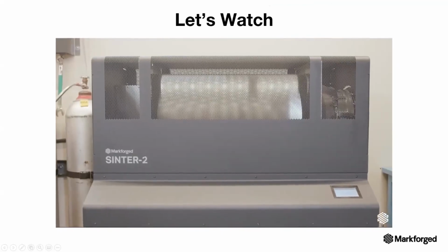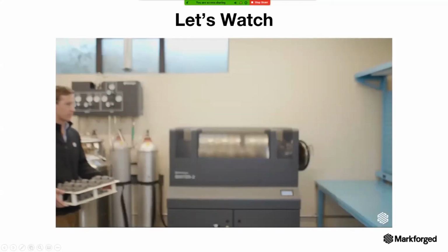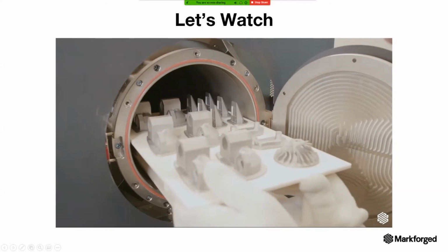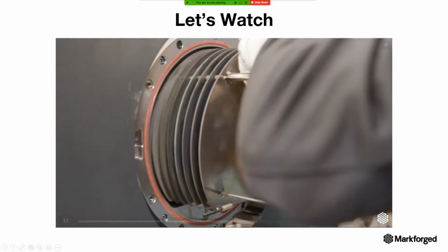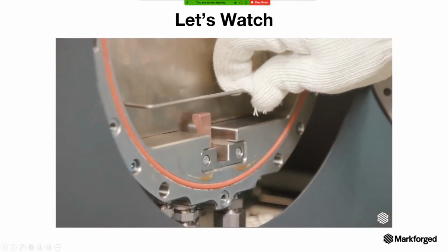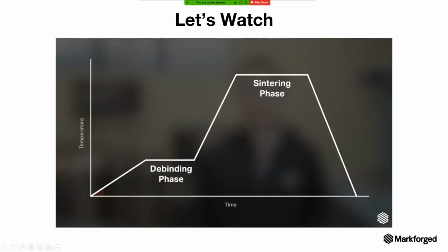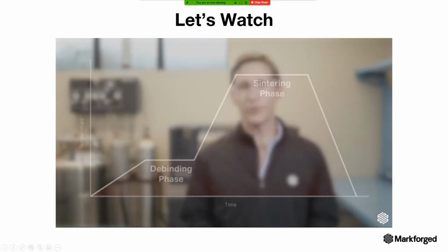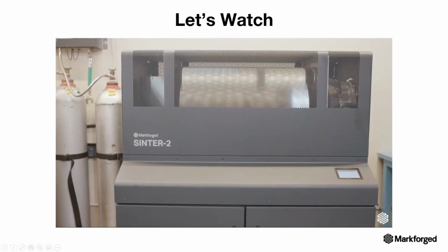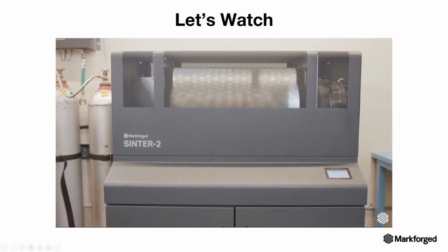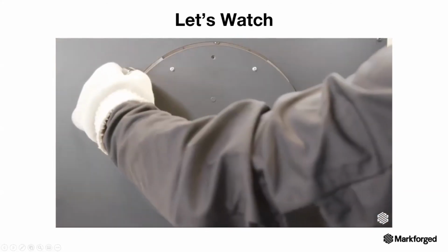This is Sinter 2, a furnace designed for mid-volume production runs and larger printed parts. Sintering transforms a print from a lightly bound collection of metal powder to a fully finished metal part. First, the temperature ramps slowly to burn away the trace amounts of remaining binding material. Then, temperature ramps closer to the melting point of the material, allowing metal particles to start to fuse together to create a strong metal part. Markforged sintering furnaces use a carbon-free retort to ensure part quality and alloy composition standards are met for our finished pieces.